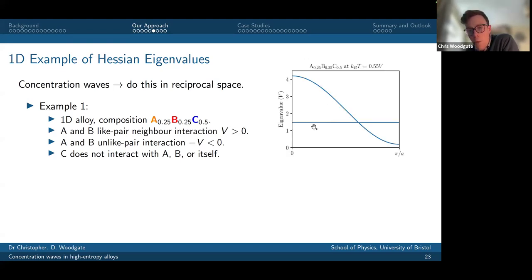Okay. And if you plot the eigenvalues of this Hessian matrix as you move around the irreducible Brillouin zone, in this case it's just a one-dimensional system, there are 2 eigenvalues because it turns out by enforcing the overall composition of the alloy, you remove a degree of freedom. And what you see is that the minimum eigenvalue occurs at the wave vector pi over a. This flat mode, I should say, is actually associated with the fact that C is not interacting with anything. So flat modes are associated generally with species which are weakly interacting.